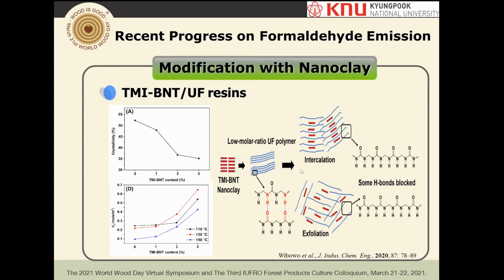Once mixed with the modified nanoclay, which has a slightly larger distance between layers, some of the UF resin molecules are intercalated between the layers of the nanoclay, and some of them are exfoliated. That means some of the hydrogen bonds in the low molarity resin are blocked or prevented, which gives a three-dimensional structure. I expect this gives a higher cohesion strength, which will obviously improve the adhesion at the end.